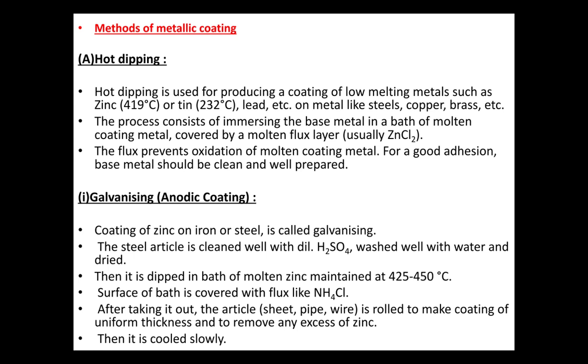The steel article is first cleaned well by treating it with H2SO4, washed well with water and dried. It is then dipped in a molten bath of zinc, which is maintained at 425 to 450 degrees Celsius. The surface of the bath is covered with flux, which is ammonium chloride, and after taking it out, the article is rolled to make the coating of uniform thickness and to remove any excess of zinc. Then it is cooled slowly.